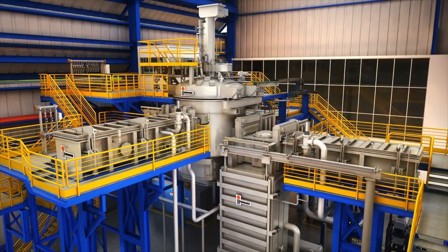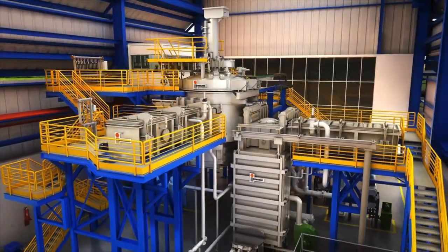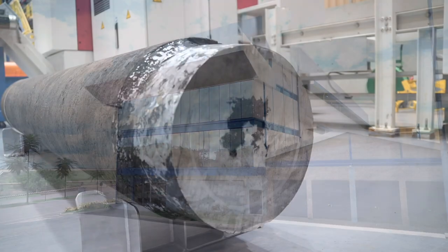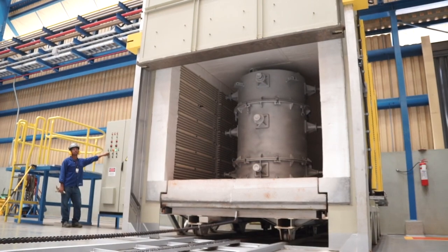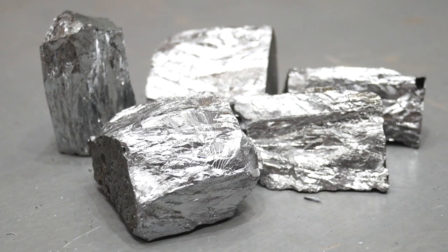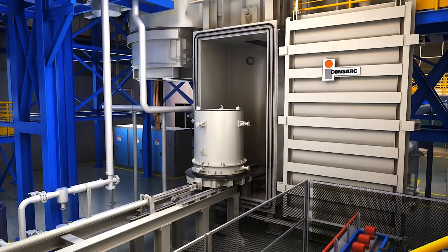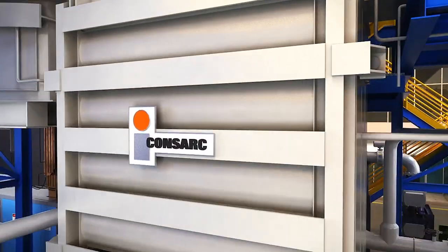To enable the development of nitride-free Alloy 718, CBMM has recently invested in developing very innovative patented technology and equipment to produce enhanced extra-low nitrogen raw materials and a test facility for the scale-up production of a superior end product. The facility is based in the company's materials and processing research centre in Araçatuba, Brazil. This capability enables the production of nitride-free Alloy 718 raw materials — nickel niobium and chromium niobium — and is also capable of producing electrodes for nitride-free 718 for vacuum arc re-melting, allowing the production of real parts for in-field testing.